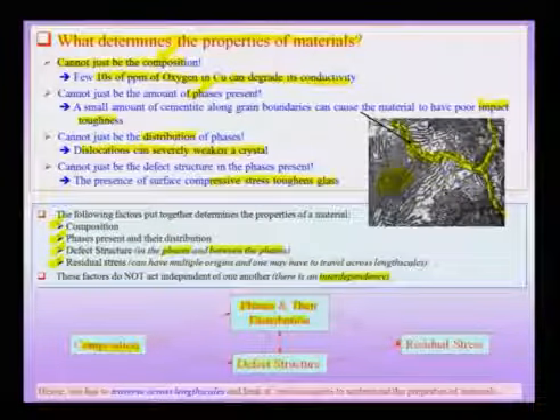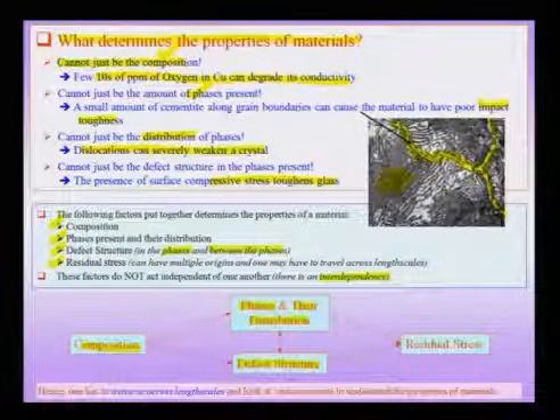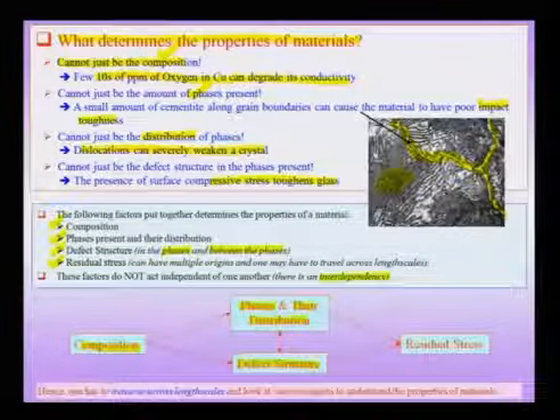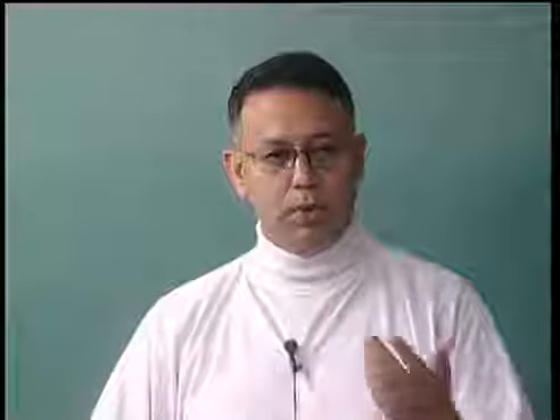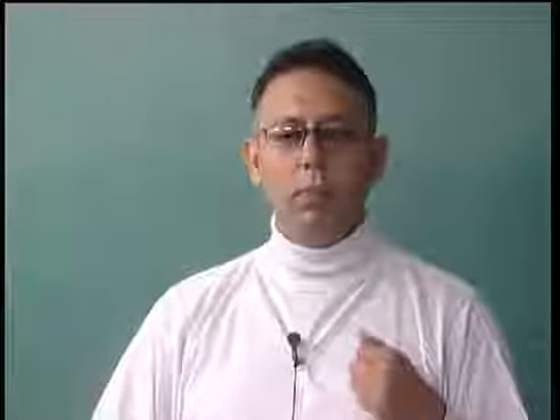Additionally, we also have to consider the defect structure of the material, which includes defects within the phases, defects at the interfaces, and of course, the unavoidable defect of the free surface, along with how the defects are distributed spatially in the material. And if you are talking about a processing technique or a long hold at high temperatures, how this defect structure evolves in service. That means you had an initial defect structure in the material at the start of the component's service, but as time progressed, it could so happen that the defect structure would evolve with time, so could the phases and the distribution evolve with time, and therefore, I need to also worry about the temporal evolution of these spatially distributed phases and defects.